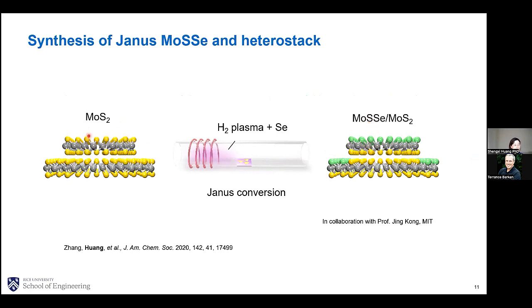So you can see we started with bilayers of MoS2 and also multilayers of MoS2. We perform a Janus conversion. So the top layer of sulfur atoms is converted into selenium atoms. Looks like this.